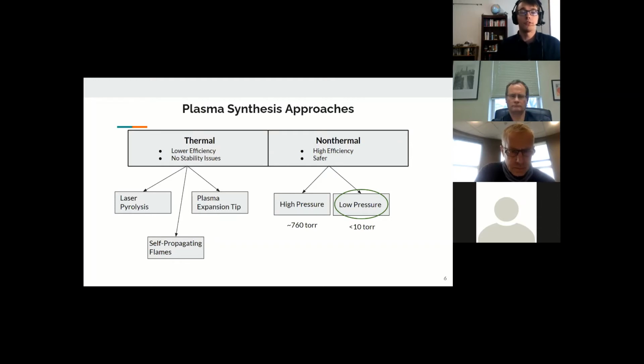Plasma synthesis solves these problems because the resultant nanocrystals are of pure form and the heat is localized to a smaller location. In non-thermal plasmas, which is the type we use, the heat is localized to the nanocrystal surfaces themselves, which creates a lot less waste heat, making it a more efficient process. Before detailing our plasma synthesis technique, I want to describe the plasma techniques of some other groups. And I'll start with the thermal plasmas.